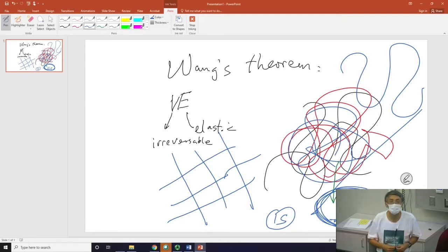if you have elasticity, it should right away come to your mind, there must be a structure that gives you the elasticity. And this structure, in this case, is the chain's inability to cross. Uncrossability. Because if they cannot cross, then the way of getting into each other's way is not so different than chemical cross-linking. Okay? So with this, I can tie everything together.